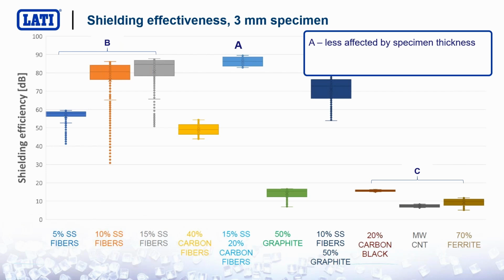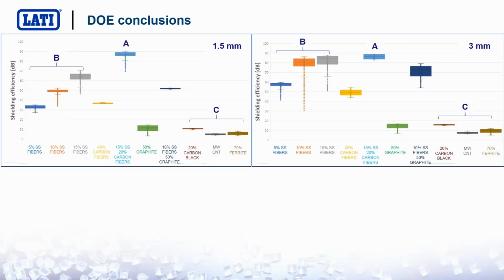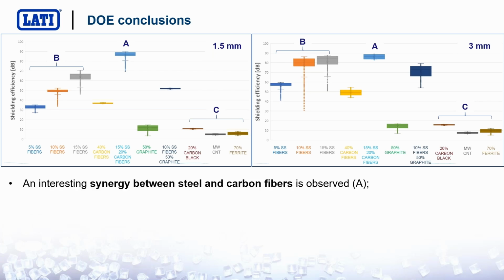Same results, 3 millimeter. You can see that the steel and carbon fiber compound is no longer affected by the thickness of the wall. On the contrary, only stainless steel boosts its performance at higher steel content and higher wall thickness. And the mixture of carbon black, carbon nanotubes, and ferrite did not show any evident difference, also increasing the wall thickness. The comparison between 1.5 and 3 millimeter thick specimens is confirming what I told you before.